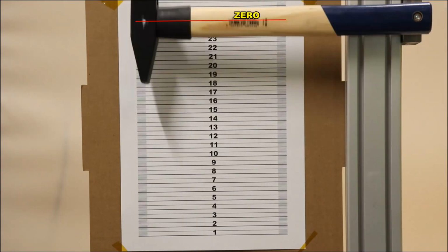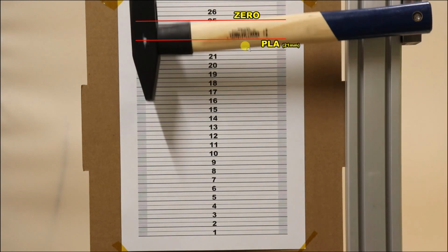This is the scale, and this is the zero position where there is no test specimen. And this is after breaking the PLA. The distance from zero position is 21 millimeters. And this is after breaking the silk test specimen. Distance is 20 millimeters from the zero position. And surprising, this is PETG. So from these three, this is the most brittle material, but PETG should be more tough.